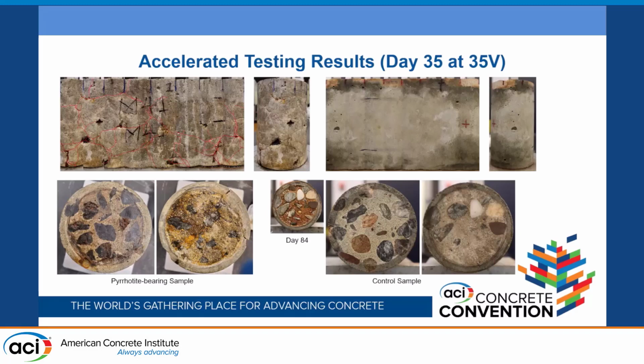But further studies are still going on into this from our materials side, and very soon we'll have clear answers for this. Now, this is our control sample. We also ran this at the same condition, 35 volts, which was the worst condition. We ran it for 35 days as well. We did not see any form of cracking in the sample, which was good.